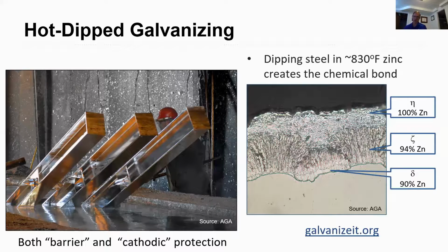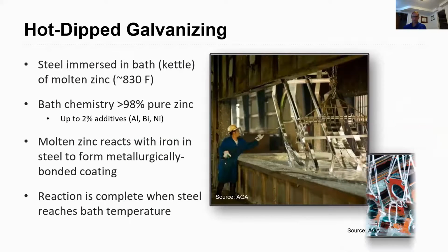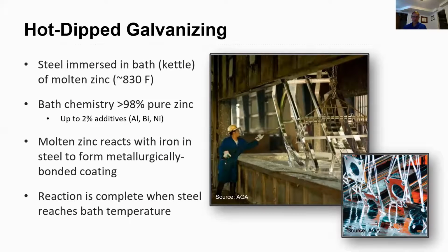But generally speaking, you take steel and you dip it in molten zinc. It's approximately 830 degrees. There's a chemical reaction here, and it mixes the outer layer of steel with the zinc layer, and they interact with one another and form a chemical bond. And the reaction is complete when the steel temperature reaches the same temperature as the zinc bath that it's in.